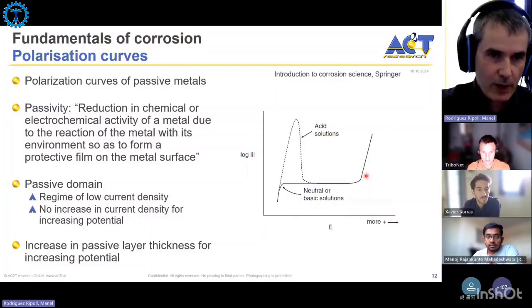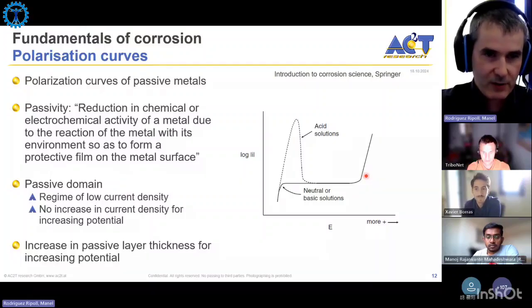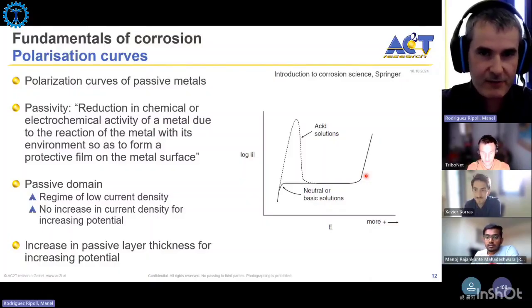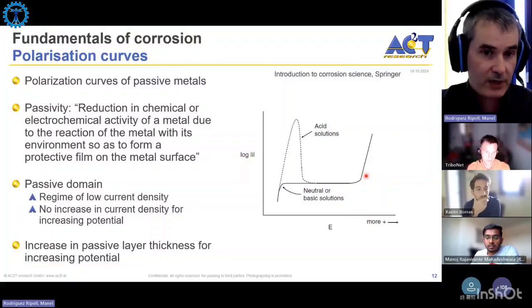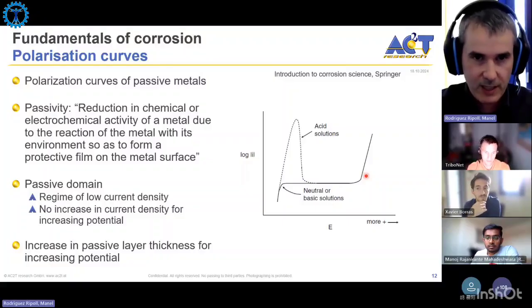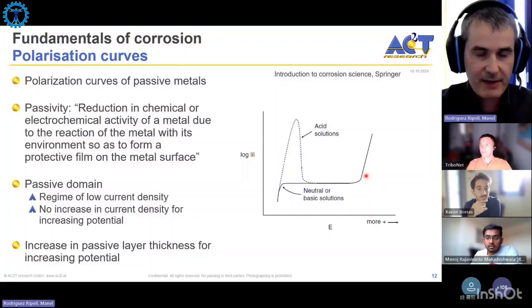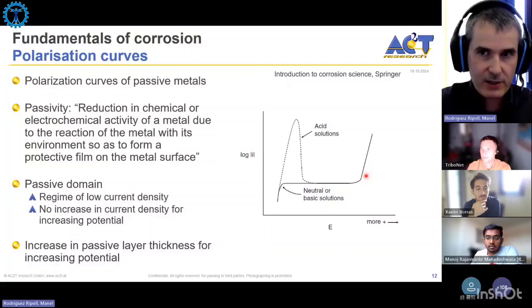So when we put a metal in an electrolyte, we dissolve the metal, we produce electrons, we have an anodic and a cathodic reaction. We may have the formation of a spontaneous passive layer. These reactions and these phenomena result in the spontaneous formation of a potential. We can modify this potential, but we need to put in an increase, so we need a driving force to change this potential. And when we change this potential by adding a current, we can make these polarization curves that give us information about the kinetics of the reactions.